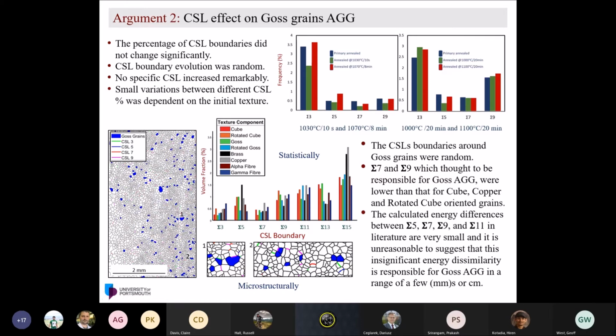sigma 7 and sigma 9, which were thought to be responsible for abnormal grain growth, were lower than cube, copper, and rotated cube. Now we didn't verify these claims by others that actually CSL is playing a significant effect on the abnormal grain growth, and microstructurally we looked at them and they were randomly surrounded by any of the CSL boundary. And from our basic calculation, we found out this actually is not reasonable to suggest a small tiny difference between the grain boundary energy, the difference between sigma 5 and sigma 7, can cause a centimeter or a few millimeter grain growth from that small difference. Then we went back to validate the high-angle grain boundary, as we will see in the next slide.